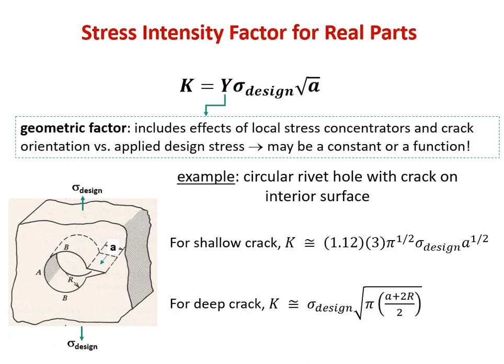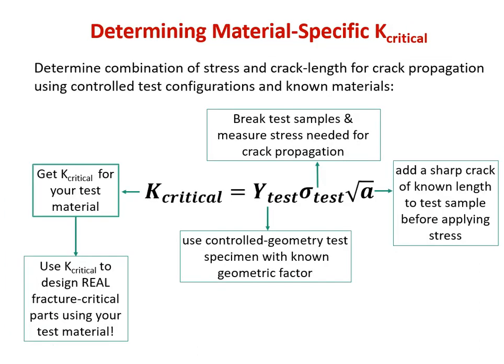How to use this in practice? You relate your probable Y to one that you can find in the literature. And in this sense, practical application of fracture mechanics and fracture toughness data is very test driven. So a lot of the magic here in designing it and applying it properly is relating your stress state and your flaw distribution to one that's been tested and verified. And we will do a little bit of practice with that.